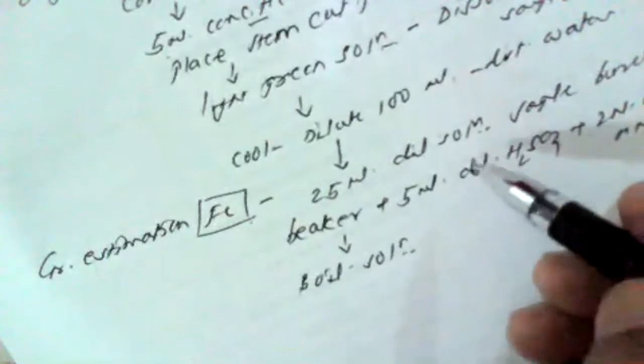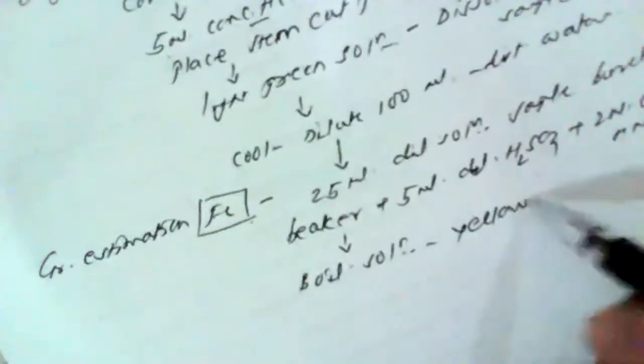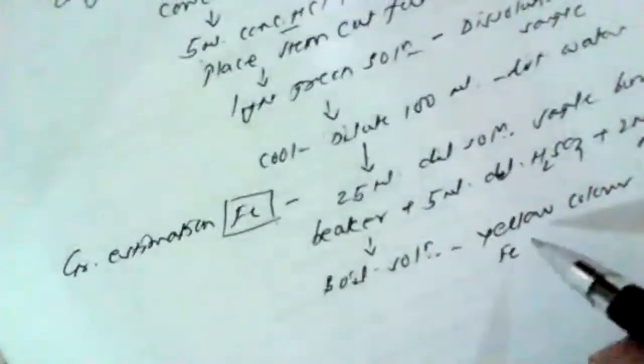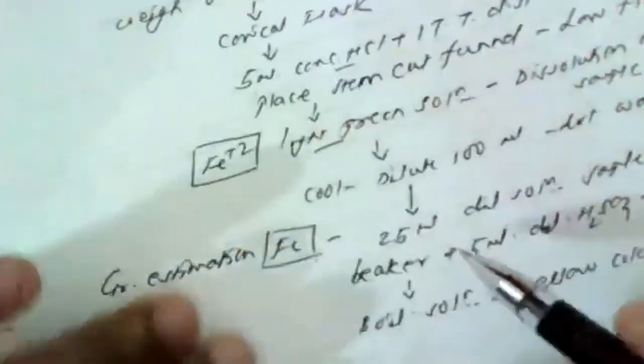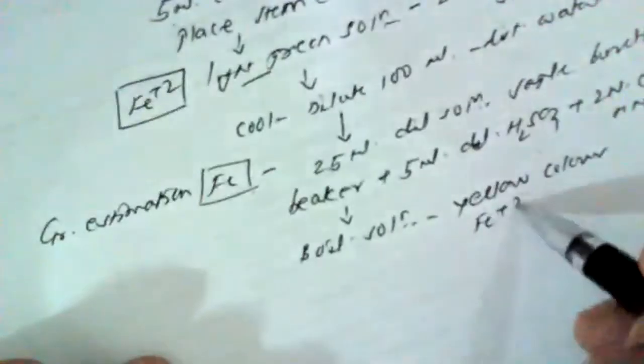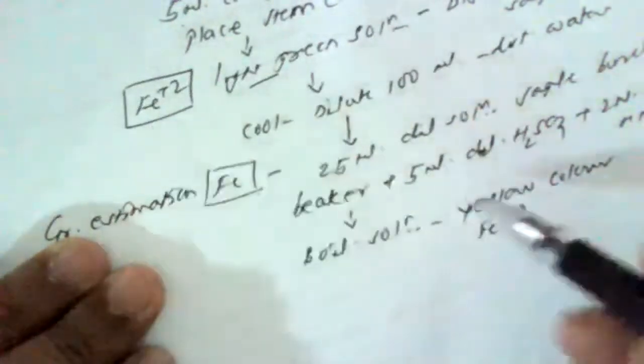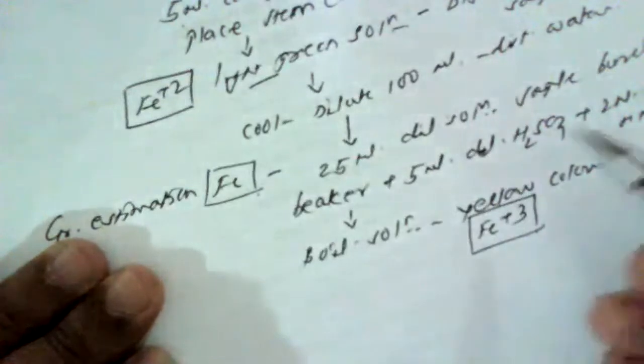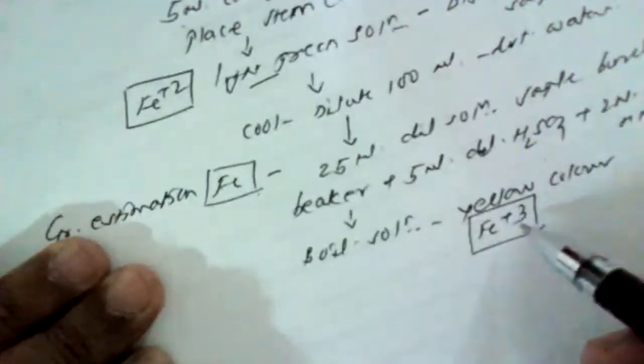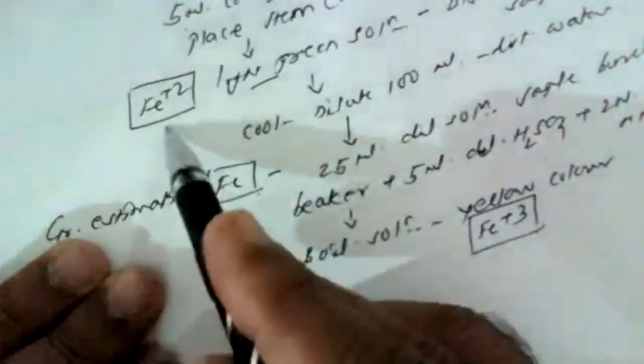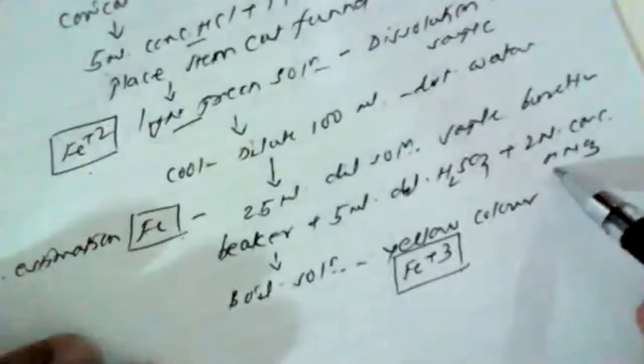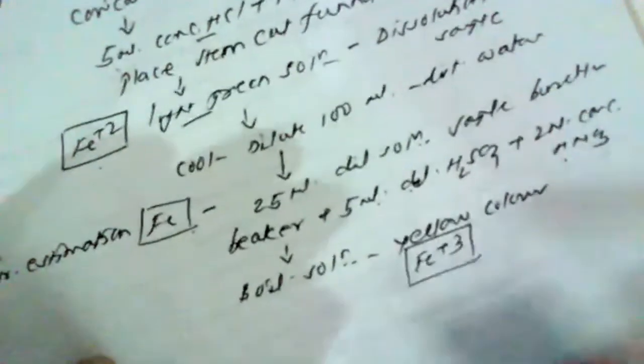Here, by adding this HNO3, that is nitric acid, we have to boil this solution till the solution turns yellow in color. That means the light green color solution that is obtained indicates that here iron is in plus 2 oxidation state. We have to oxidize the iron into plus 3 oxidation state, and we know ferrous salts are light green in color. For example, ferrous sulfate crystals we have seen in the laboratory, while ferric chloride solution is brownish yellow in color. So when the solution turns yellow in color, this is a perfect indication that almost all ferrous ion is oxidized into ferric state. So nitric acid acts as an oxidizing agent. So 25 ml diluted solution, 5 ml H2SO4 and 2 ml concentrated HNO3. After boiling for about 2 to 4 minutes, the solution turns yellow in color.